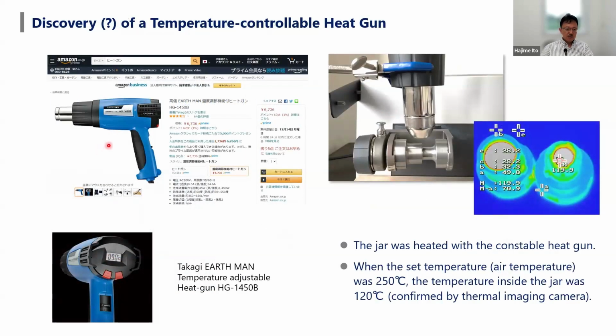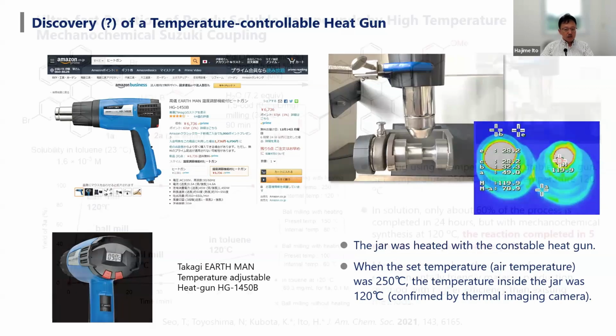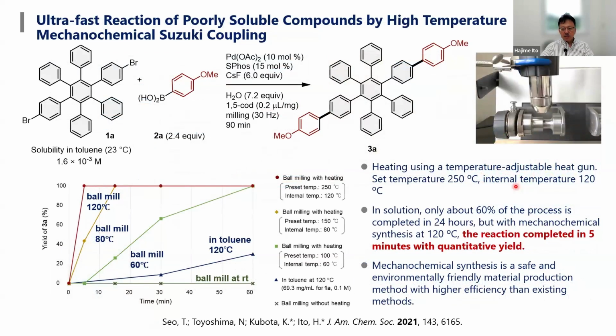Finally, I found a temperature-controllable heat gun on the Amazon marketplace, which is very useful. Just by changing the air temperature, we can control the inside temperature of the jar. In a typical case, if we set the air temperature to 250 degrees Celsius, the inside temperature should be about 120 degrees Celsius. This temperature can be checked with a thermographic camera, as shown here. So heating up the jar is very powerful for ball milling cross-coupling.